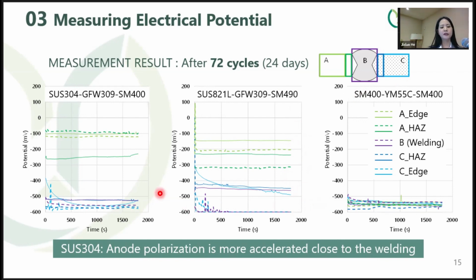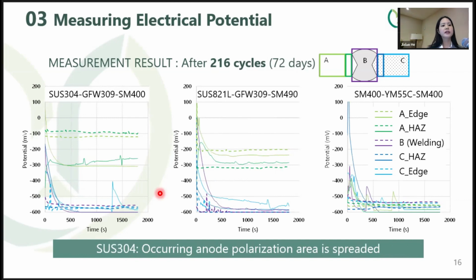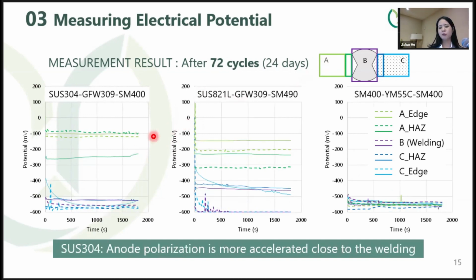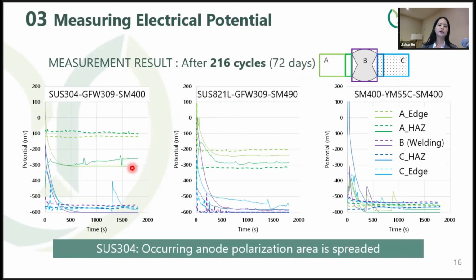For SUS304, anode polarization is more accelerated close to the welding. And when more accelerated, in 216 cycles, as shown here, the potential on the SUS304 side is much lower. SUS821L is still a little bit higher than initial, but compared to this one, it's a little bit lower. So it can be the state where electron exchange is occurring. Right now, for 304, the anode polarization area is spread, I guess. And for the SUS821L specimens, I'm trying to figure out what happens by analyzing the composition and structures.